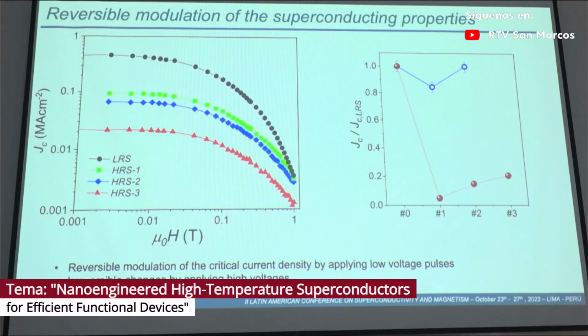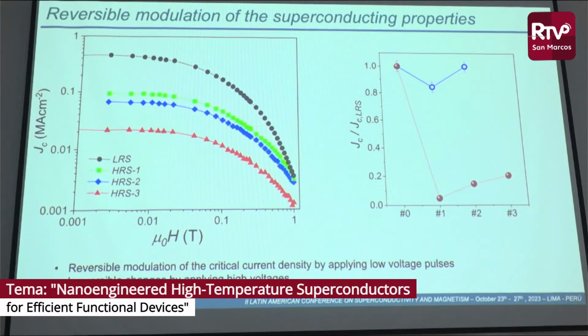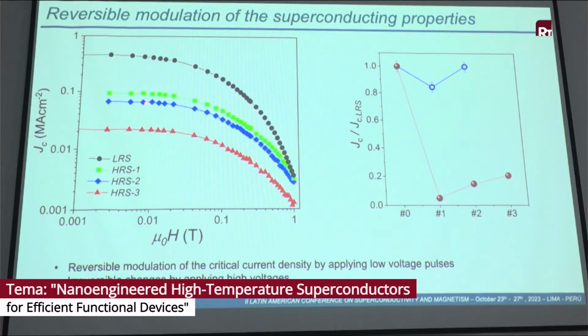And finally, what we have explored is what happens with the critical current density in the system when we change the oxygen. Here I show JC versus the magnetic field for samples; this would be the pristine state, and these would be different samples that were shifted to the high resistance state. And what we see is that we reduce the critical current density, and the critical current density versus field has different behavior depending on the oxygen content.